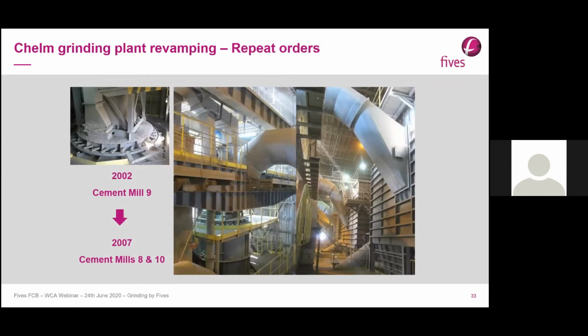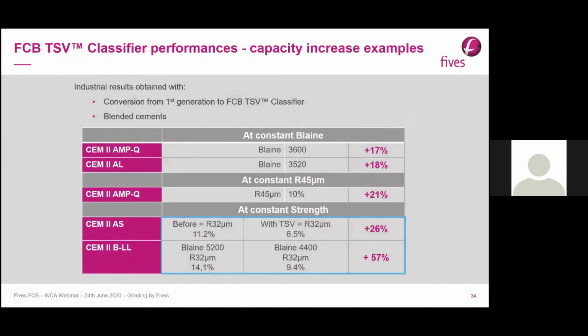Five years later, the performance and reliability of the TSV led the customer to repeat the order for 2 other mills with the same TSV. Here is a panel of capacity increase with the same scenario, starting from conversion from a first generation dynamic separator to a TSV classifier. For example, for constant strength, which is the end goal of the customer, the quality of cement, the capacity increase is between 26 and 57%, with these two examples.